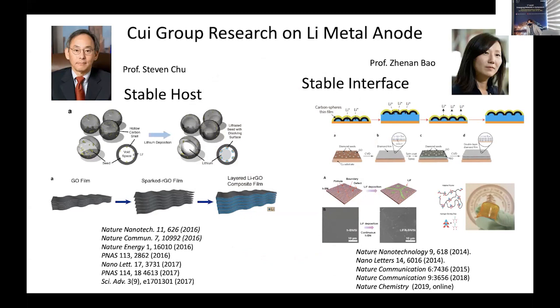We learned from graphite how graphite works. Graphite is the host for lithium ion. We could construct hosts, but the host will be very different from metallic lithium. In 2016, we published several papers to propose and demonstrate for the first time a metallic lithium host. Now, many research groups around the world are using the host concept for metallic lithium and also metallic sodium and other metallic anodes. And then the interface is also very important. What's the nature of the interface we want? We want it to be mechanically strong, mechanically resilient, as well as chemically stable. Remember, lithium metal is so reactive. Without mechanical and chemical stability right there, you will not be able to have a stable interface.